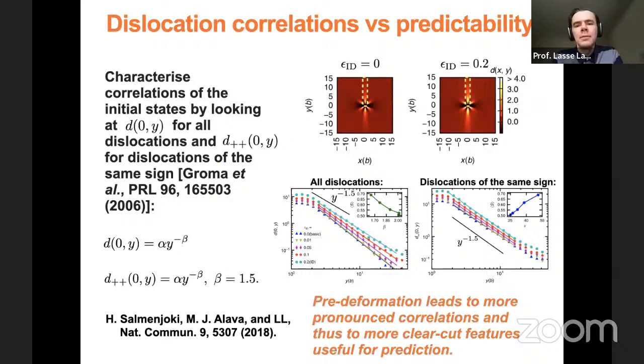And then we can also look at the effect of predeformation. Here the point is that if you apply some stress and deform your samples, you actually induce some structure formation in your dislocation system, which then shows up as more pronounced correlations of the dislocations. So you can look at the pair correlation function of the dislocations, and you see that these become more pronounced as you apply some initial deformation. What this means is that these structures become more clear cut after you have applied some pre-deformation. And that means you have more clear cut features that the machine learning models are able to use for prediction.